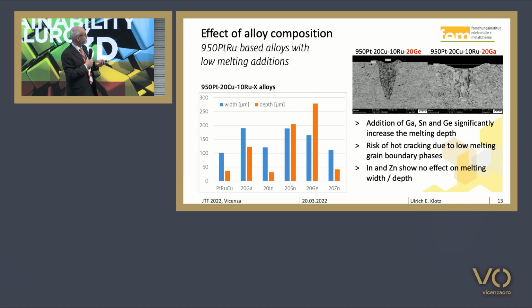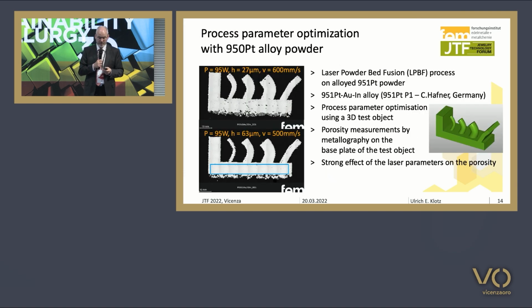However, indium and zinc show no effect, which was a bit surprising for us, but that was the observation that we also confirmed when we worked with alloyed powder. So in the second step of the study, we used alloyed powder.